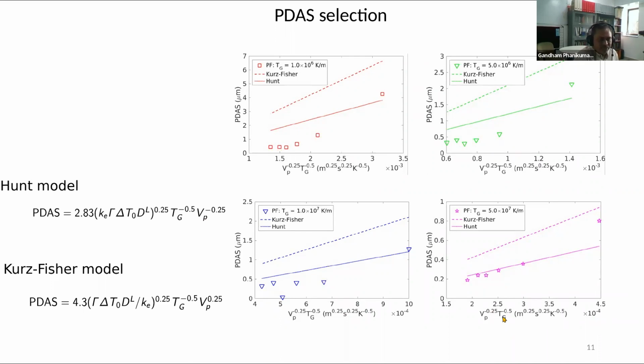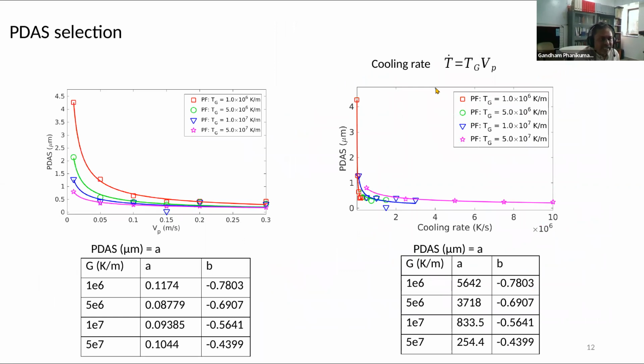Okay. So if you are changing the temperature gradient or if you are changing the velocity of the laser, then how does the primary dendrite arm spacing change? So that variation can be calculated based upon some simulations that you have done, and later you can actually use it for extrapolation. So that is the idea. Now, if you change the cooling rate also, these things will change, which means that if you play with, let us say, a helium, removing the heat from the laser printed component compared to, let us say, argon, then cooling rate is more with helium. And how does that affect the microstructure is something that you can predict by doing these simulations.